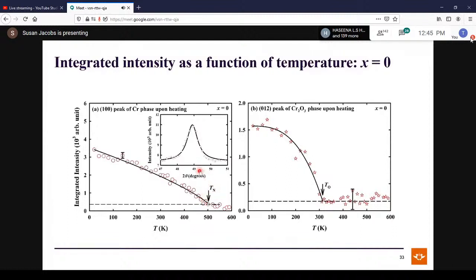Now, because we have 2 magnetic peaks, one belonging to the chromium oxide phase, we also did the integrated intensity for that to find TO, which is the transition temperature of the oxide. Okay, so that was for the alloy with no vanadium.